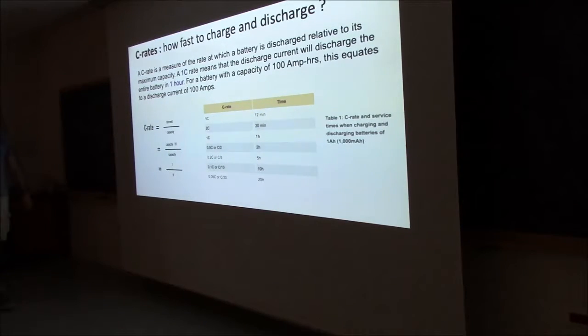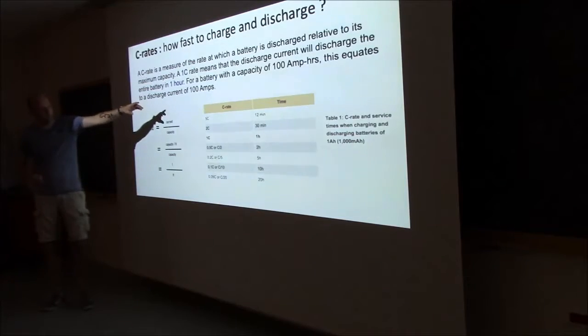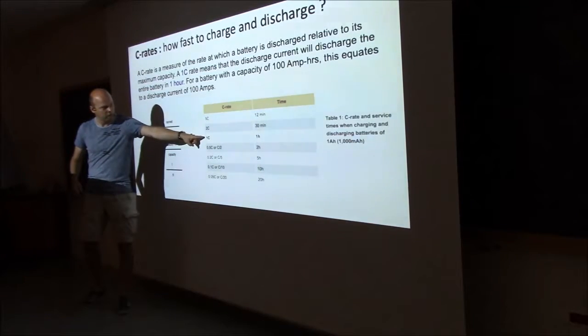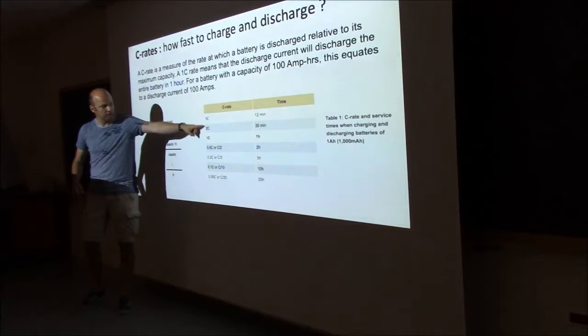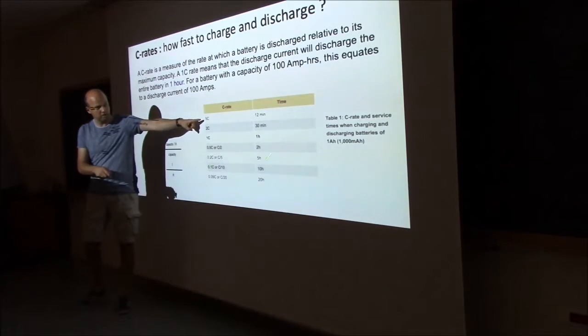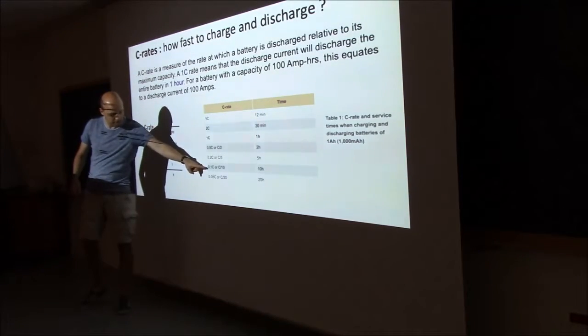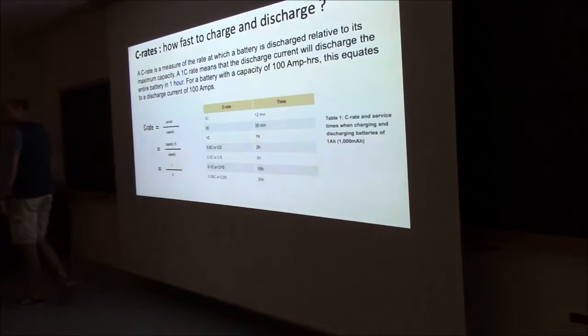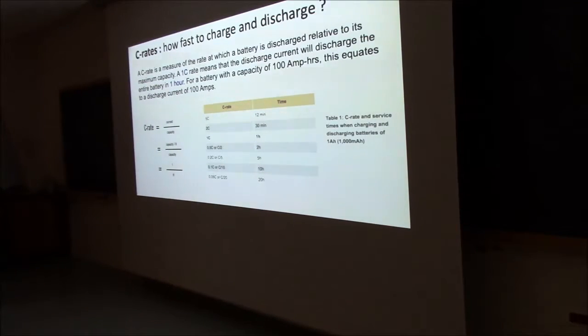So what you do then is you study, if you have 1 C, you do that in an hour. If you have 2 C, you do it twice as fast, 5 C, 5 times as fast, so it takes less time. But for a lot of the battery studies, people go to 0.1 C, so C over 10. You do it very slow, but then these measurements, they take forever. Luckily, as we deal with thin films, we can already get all the lithium out if we use, let's say, values around 1 or 2 C. And even higher, they can withstand it.